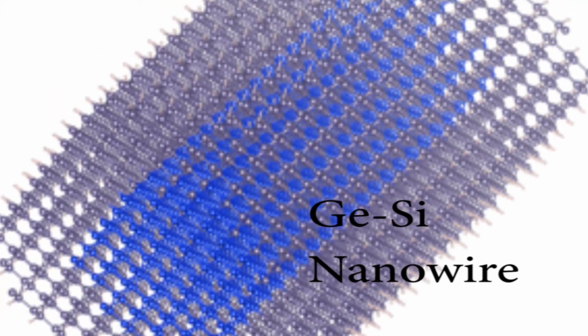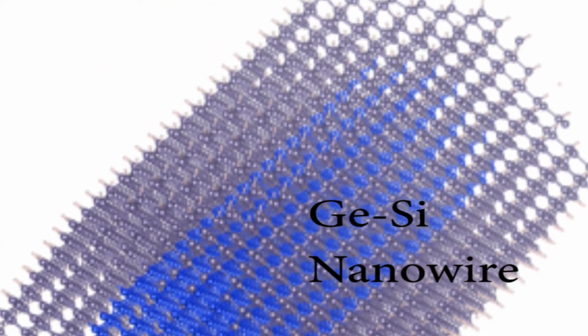However, to do that, we have to be able to understand what their properties might be, and that's where my modelling comes in, because we can take the nanowire, we can actually build them physically in a computer, add in different atoms, say boron or arsenic or phosphorus, to change the conduction properties, and also particularly see what happens when you put those elements in different parts of the nanowire. So if you have a silicon center and a germanium outside, and you put the dopants into the germanium, do you get very good conduction in the silicon? That's the kind of question we might ask.